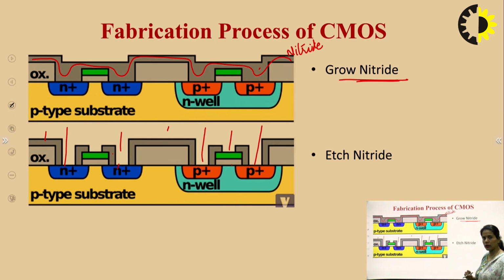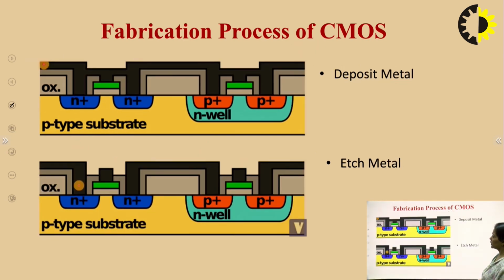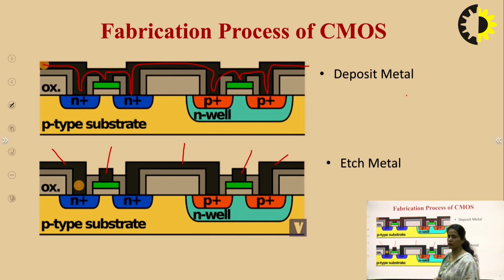Again, using the patterning and etching, the nitride is removed from these portions, because here the metallic layers have to be grown. In the next step, after etching, the metallic layer is grown all over the surface. So this is all the metallic layer. Now after depositing the metal, we have to etch the metal in the desired locations. And what are the desired locations? So we have to leave the metallic layer only here, for the source areas, for defining the source interconnects, for defining the gate interconnects, and this is for drain connections.